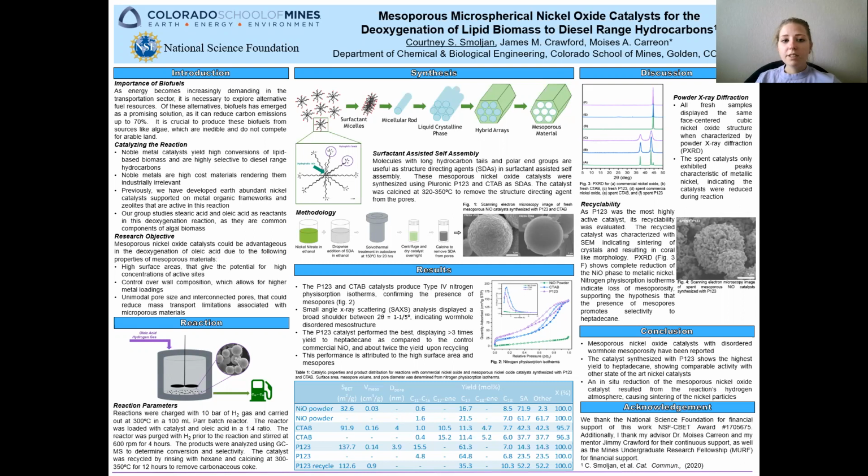In the past, our group has studied zeolites, which are a silica alumina microporous framework, and we've loaded noble metals onto the framework, and that was used as our catalyst. Some of the drawbacks that we see from these kind of catalysts is they're really expensive with the noble metals, and zeolites can cause mass transport limitations because they have such small pore sizes.